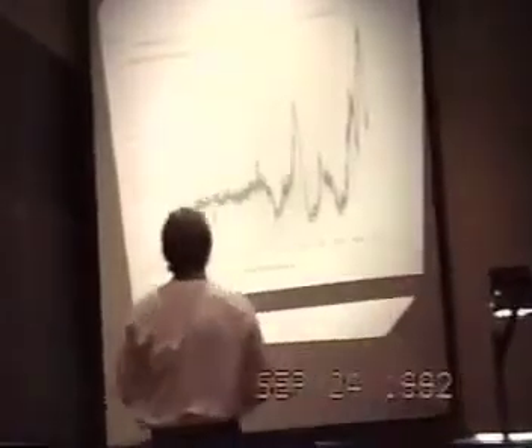In this case, we observe the outlet temperature sensors, the two of them, sometimes they move apart a little bit and you can see the variation. The two outlet temperature sensors were not constant for this period of time, suggesting that within the calorimetric boundary, there is a source of unaccounted for excess power. And if we calculate that from the equation, we can see this effect.